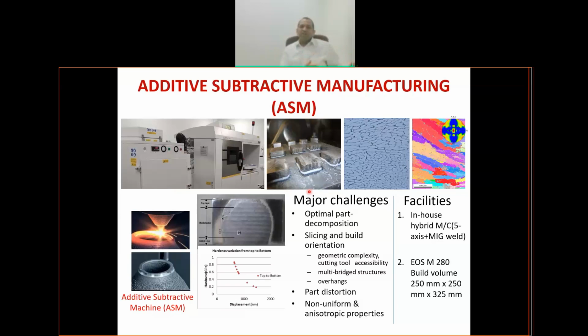All the traditional alloy systems are equilibrium alloy systems or metastable equilibrium. But now suddenly we can go to non-equilibrium alloy systems. And that opens 1,000 times more alloy systems than what we have so far been exposed to. We haven't been able to really explore all of them. And we are just scratching the surface. So this is one very big advantage of additive manufacturing, which just is not possible through conventional manufacturing. The other big advantage of additive manufacturing is that you could have a customized part. So every single part can be customized.